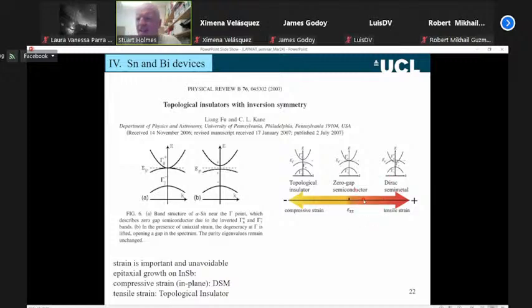Depending on the size of the strain, the alpha tin lattice constant is larger, so it has to be compressively strained to grow epitaxially on indium antimonide. It's compressively strained in plane, so the out-of-plane component is a tensile strain. That should send the system into something like a Dirac semimetal, something that looks a little bit like graphene. So strain is important in these materials. It turns out it's unavoidable. You have to grow it on some substrate, so the strain aspect will be unavoidable.